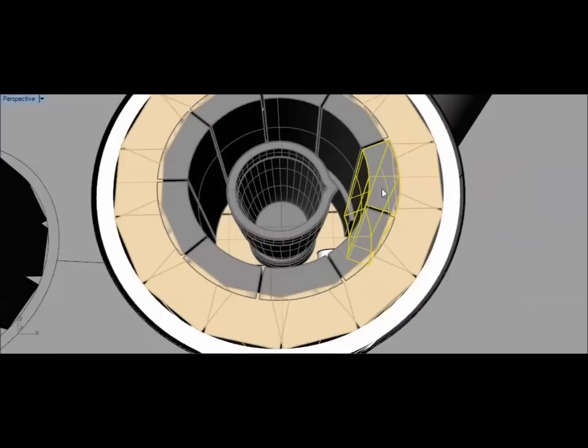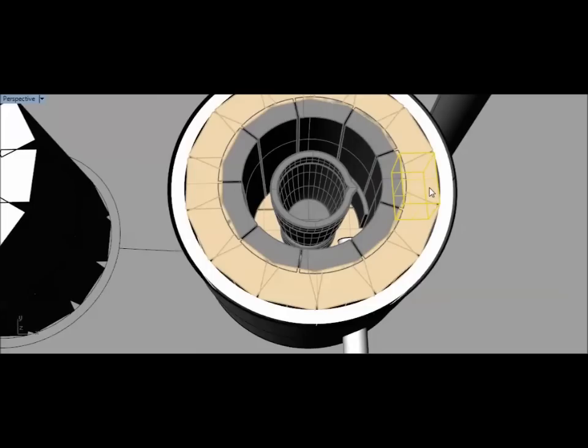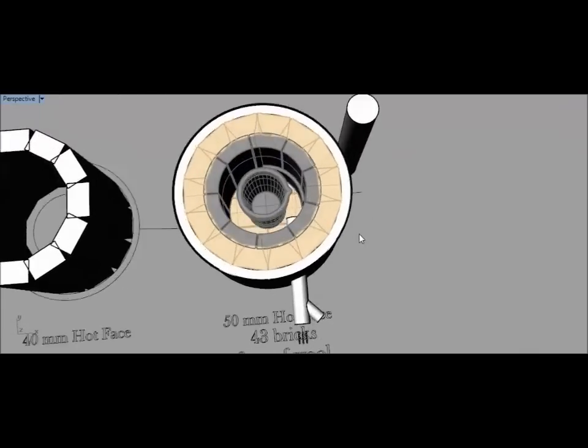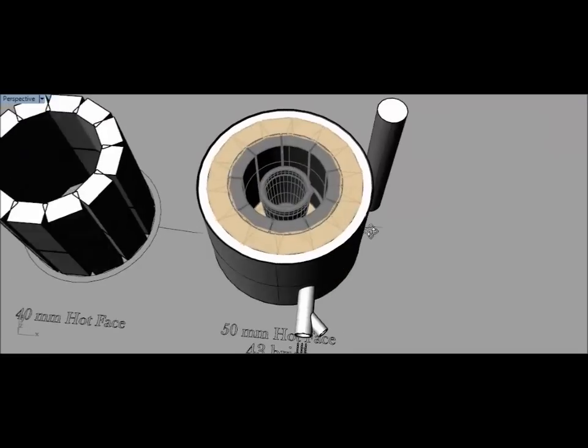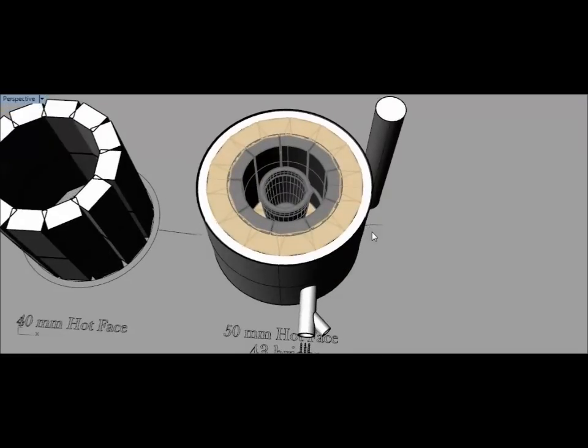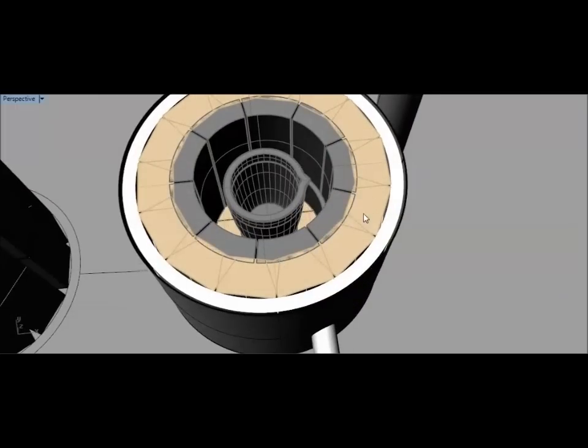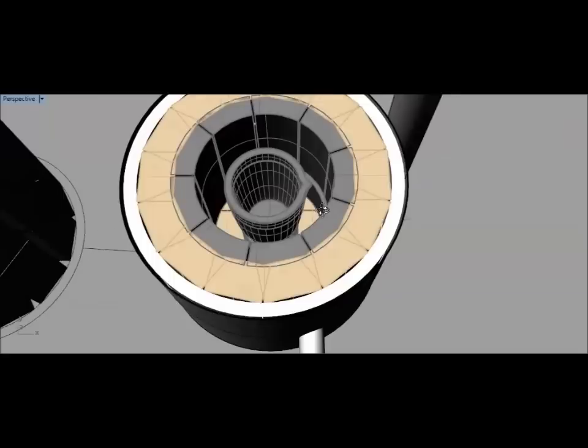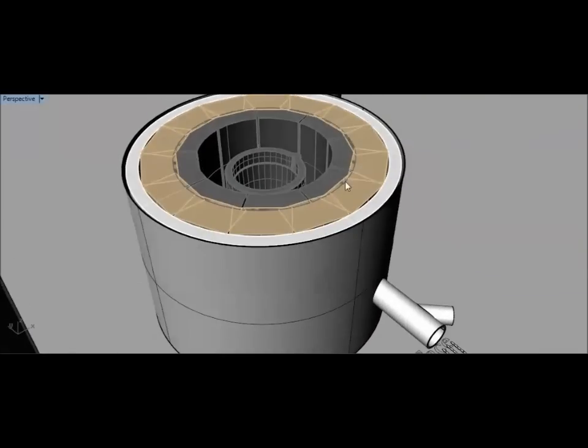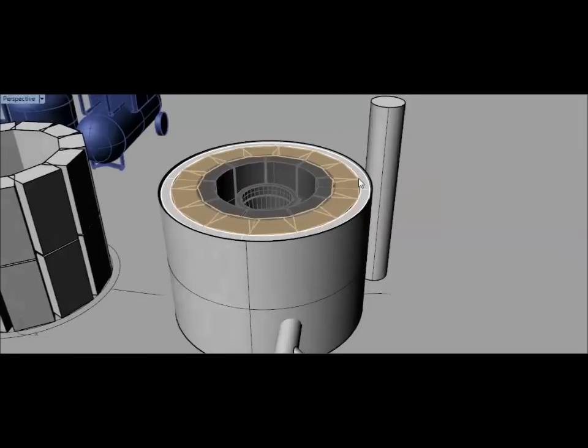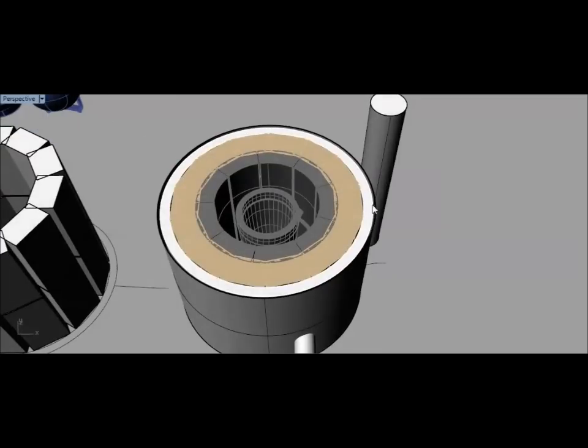So these are the hot face, made of castable. And this section, is also a castable. When I say castable, it's a mixture of calcium aluminate cement, and a whole lot of other goodies that make it workable. Calcium aluminate cement is really hard to work with. It's a pain in the ass. I've already done it, and, oh, I'm not doing that again. To give you an example, I was putting in water, with a spray bottle, because it was that sensitive to over-wetting. Like, tss, tss, tss, tss. You know, it's just, stupid. So, these are pre-made, in bags, with all the goodies, deflocculants, and montmorillonite clays, and all sorts of stuff that make it really easy for the average mug like myself, to do something good. Good. Over here, obviously, is the wool, the white bit, white, that one, yep. 25 mil, so about an inch.